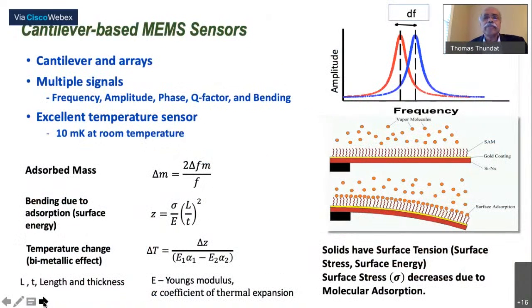So the way cantilevers work, the cantilevers and cantilever arrays, they can give you multiple signals: the frequency, amplitude, phase, Q factor, bending. And they're also excellent temperature sensors. It can have a sensitivity around 10 millikelvin at room temperature without any cooling, using the bimetallic effect.